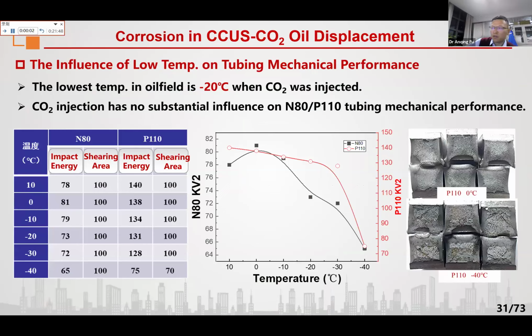The last one is the influence of low temperature on the tubing mechanical performance. Why do we concern about the low temperature situation? Since the injection of CO2 will lead the temperature to drop as low as -20 degrees C. Based on our research, CO2 injection had no substantial influence on the impact energy of the tubing. Well, there was no substantial influence. So right now, we don't concern too much about this kind of scenario.